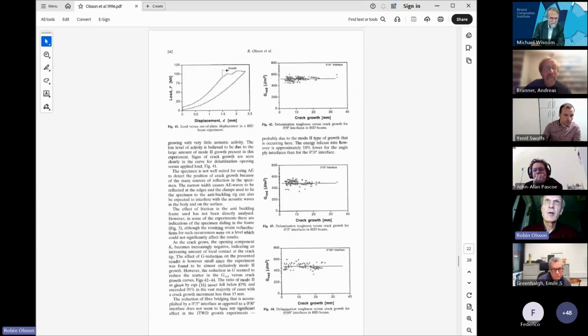And we looked at delamination growth in a 0-0 interface, in a 0-5 interface, and in a 0-0-90 interface. The interesting thing is that in these tests, we get stable delamination growth, and you can see that the values are very similar for all the different interfaces. The difference was that for the 0-0 and 0-5 interfaces, you have a much higher initiation value. But for the growth, they were all similar. Of course, this was a growth where the delamination plane was trapped between surrounding 0-degree plies.